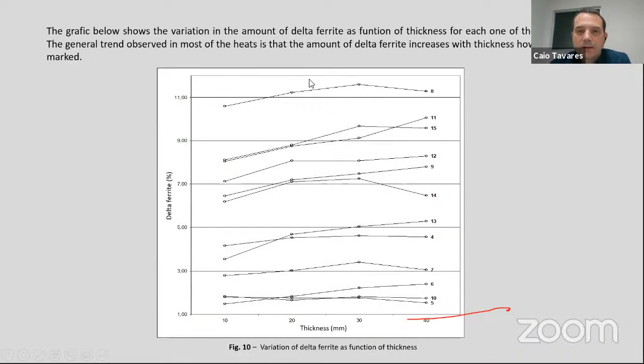So then a graphic was created to evaluate the variation of delta ferrite against the thickness. So we have here those 4 thicknesses, 10, 20, 30, and 40 millimeter, and the amount of delta ferrite that we observe in each one. In some samples, we saw an increase of delta ferrite according with the thickness, but in some ones we didn't see too much variation. So the effect of delta ferrite in the thickness is not very marked or pronounced.